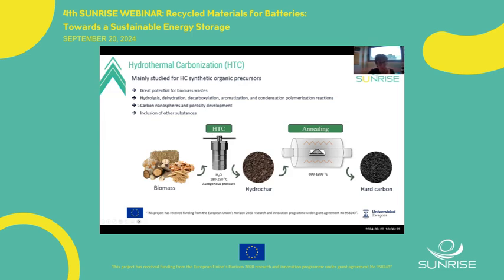Inside, several reactions take place, such as hydrolysis, dehydration, decarboxylation, and polymerization reactions. This gives rise to different morphologies in the carbon, such as the appearance of carbon nanospheres, and also the development of porosity. This process also allows us to include other substances to dope the hard carbon, for example metals. Then it's compulsory to perform another pyrolysis step and an annealing step at higher temperatures in order to provide enough electronic conductivity to the material to be used in batteries.